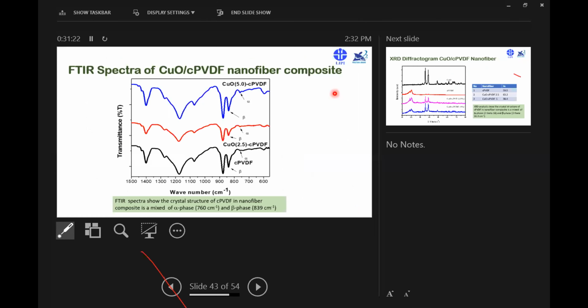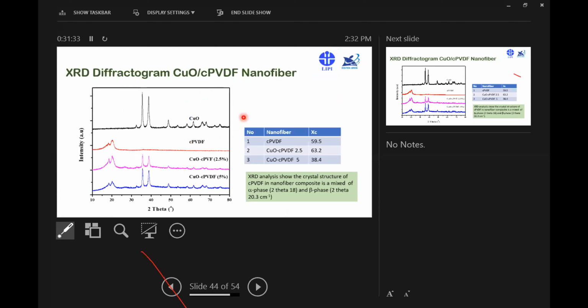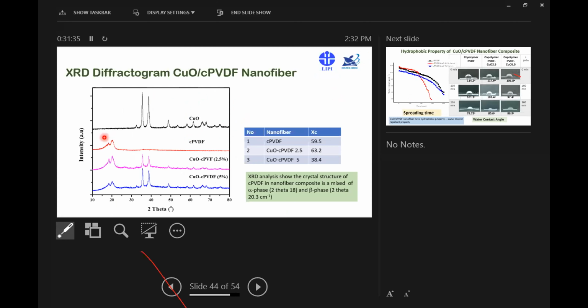You can see here this is a mix of beta and alpha crystal phase in the composite, in the polymer. And the same result you can see here. This is around 2 theta, around 20 is about beta phase, and 18 is alpha phase. So the crystal structure is a mix of alpha and beta, but it's dominantly beta phase.